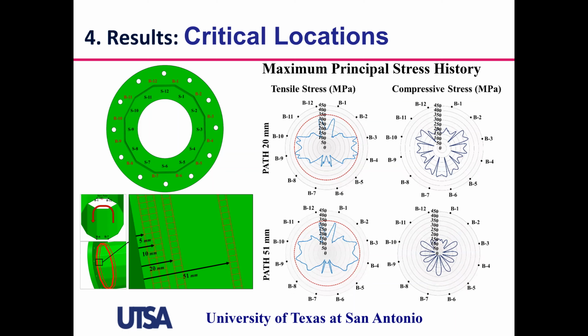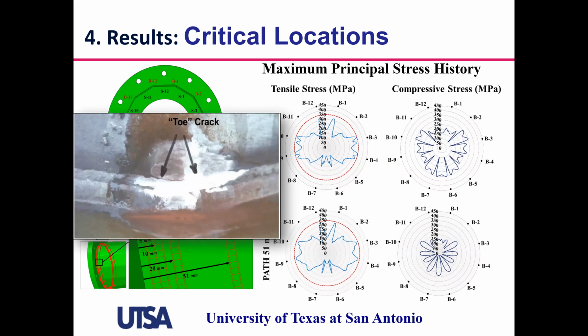But an important observation is that from our models, we were able to capture the location of potential weld toe cracks, because as you can see, the spikes of the stresses are always at the bends, particularly bends 3 and 10.